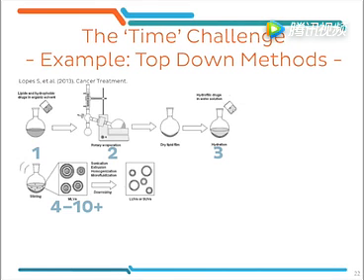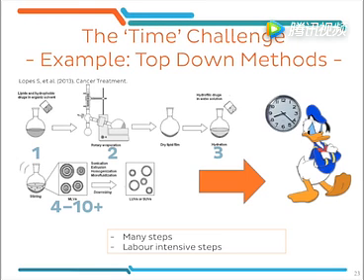And then the thin lipid film is rehydrated with an aqueous buffer, and that results in the formation of large multilamellar vesicles. And these large vesicles then further need to be broken down into a smaller size, for example, by applying sonication or extrusion or high-pressure homogenization or other methods.